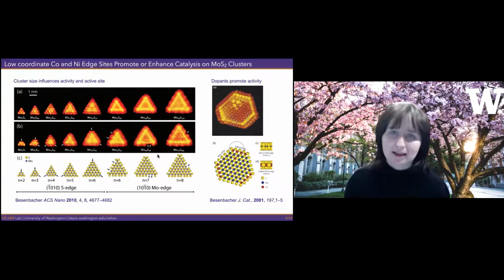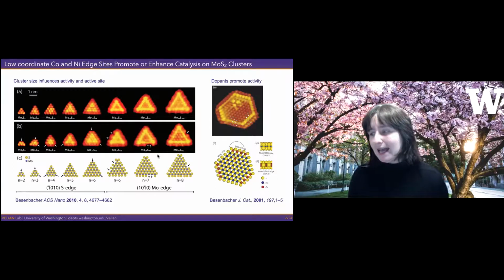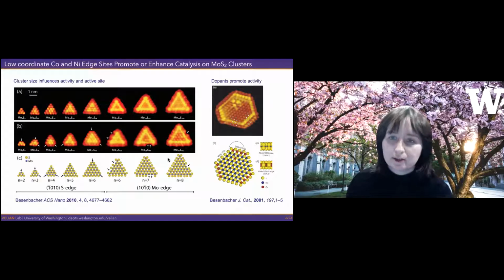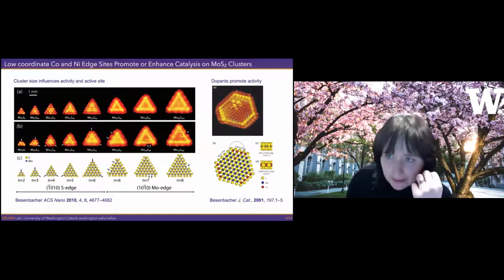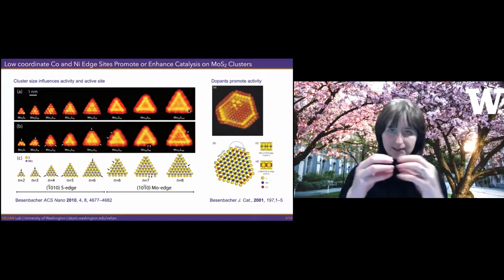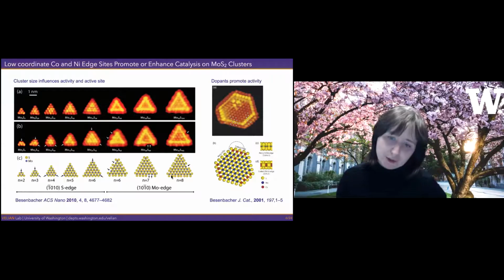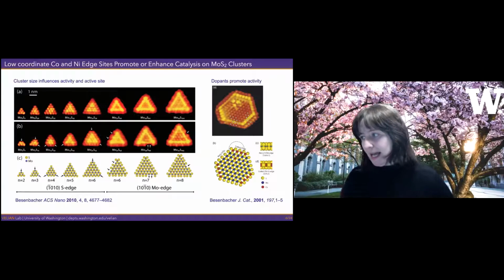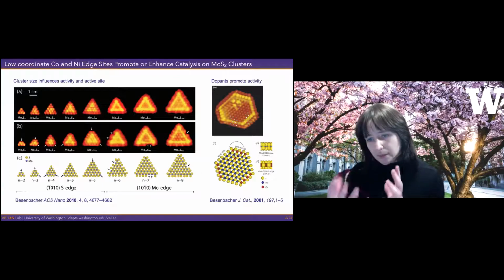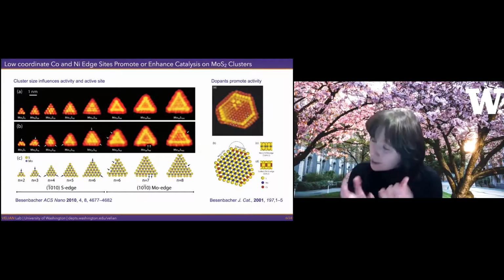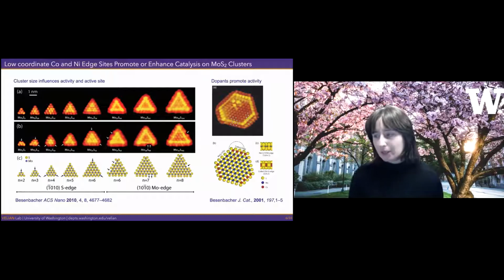It's an excellent catalyst for hydrotreating. And it turns out that the crystallites that are most active in this transformation are single layer molybdenum disulfide flakes. So this means that literally you have a single layer of molybdenum sulfide. It's a layered material, and we see here a projection of what it looks like at different dimensions from top down. And so typically the most active crystallites are 2 to 3 nanometers in size. So that's pretty small actually in operating conditions.